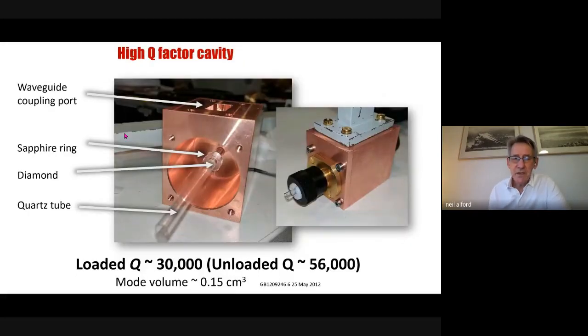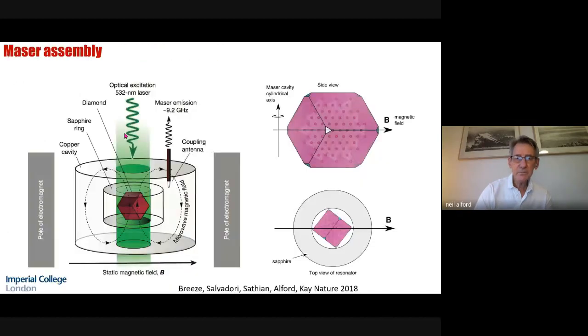And so we built a high Q cavity. You see the copper cavity there, and we have a small sapphire resonator, which has a loaded Q of 30,000 and an unloaded Q of 56,000. And we calculated that that Q, with the Purcell factor that the sapphire offered us, would give us the threshold for masing. And you can see that we put the diamond inside the sapphire ring, right inside the high Q cavity. And so here is the setup. You can see the little red diamond inside there. And actually, it really is red because of the nitrogen vacancy defects.